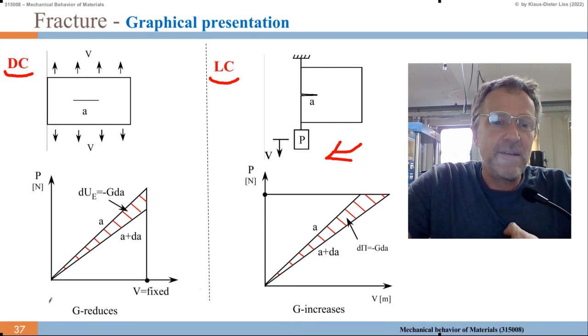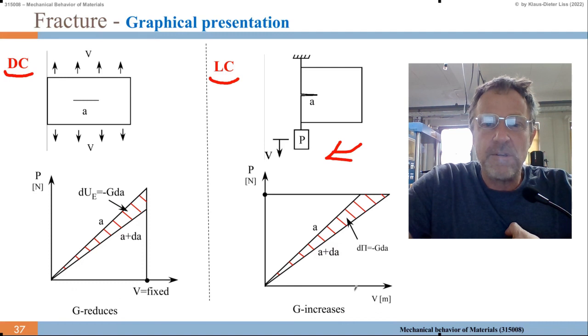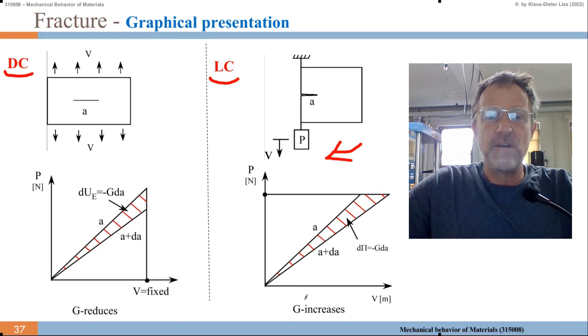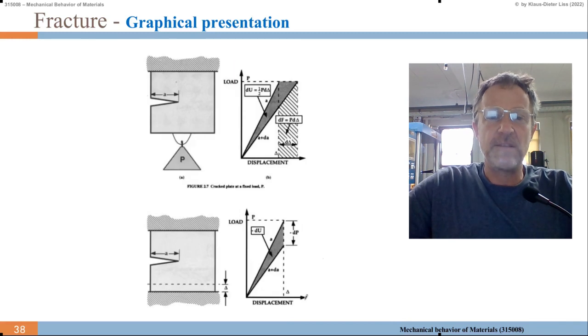And that's why on the left, the G reduces under the critical G at some stage, and the propagation of the crack stops. While under load control it increases and increases, and we already know it increases with the third power of A, the length of A.